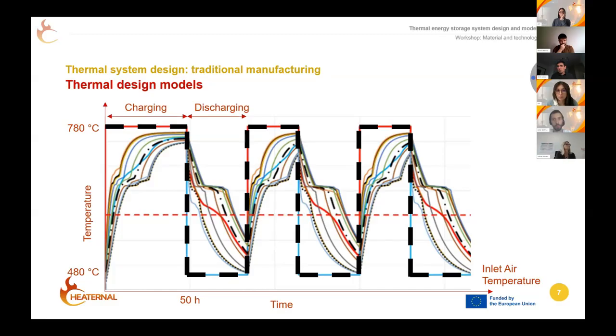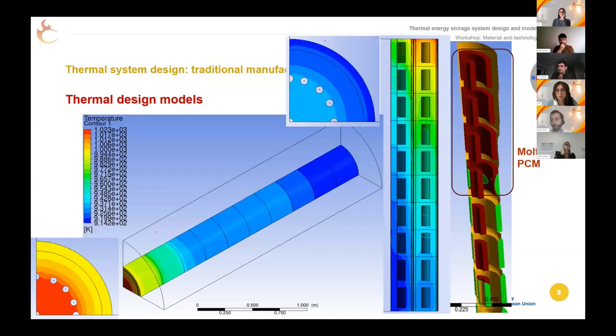How do these thermal models look like? Well, we have different levels of complexity, because the more complex you make your model, the longer the calculation time will be. And this is, I think, the more complex one. So it's a CFD model where we've simplified our airflow a bit, but the heat transfer in the ceramic and PCM is simulated in a finite volume method. You can see a quarter of the system modeled with 10 bricks in total. You get temperature fields, and if you look on the right-hand side, you also see that you can track what PCM volumes have molten over time. We make geometric adaptations and check with these models to obtain an optimal solution for a specific problem.